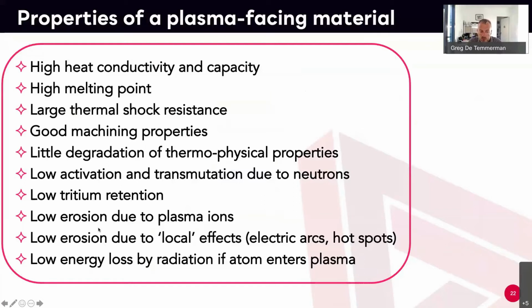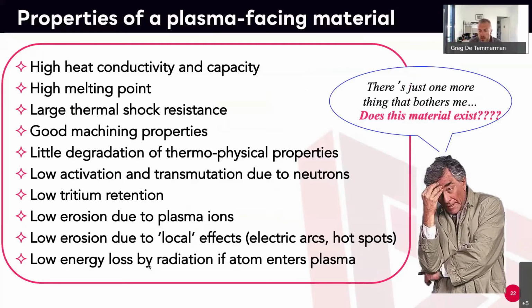I want it to be resistant to erosion because if my material erodes too fast, I have a lifetime issue. I want also to be resistant to local effects. We can have a lot of electric arcing, hotspots, and so on. And I want that if the atoms are penetrating into the hot plasma, they should not contaminate the plasma too much. So when you look at this list and you try to think, is there a material which is actually ticking all boxes? Well, the answer is no. So you have to make do with whatever you can and choose which parameters you actually optimize and how you can find a compromise between the plasma and the material.